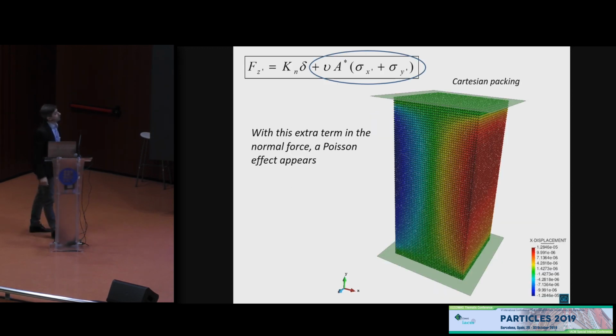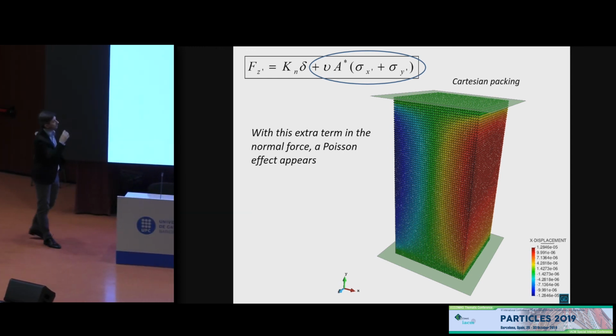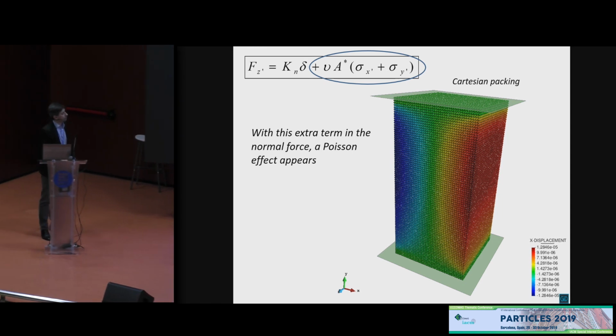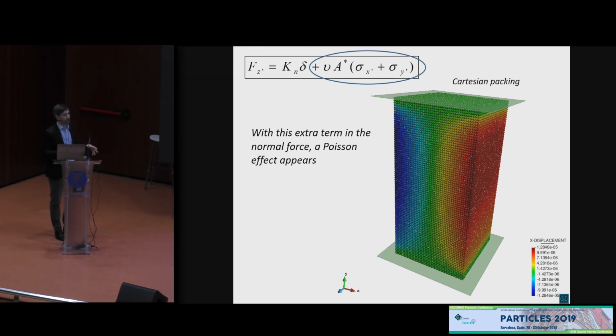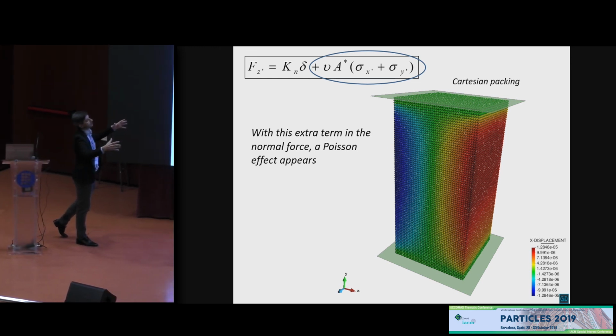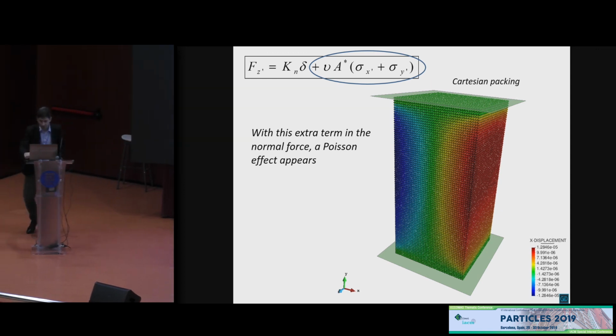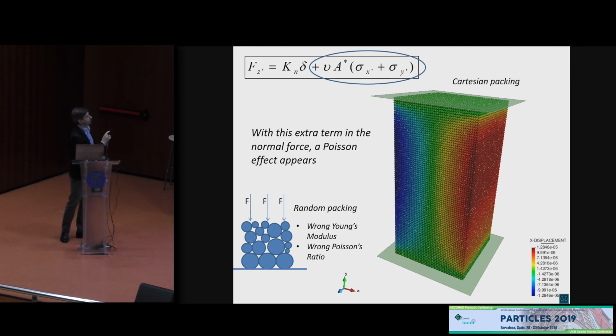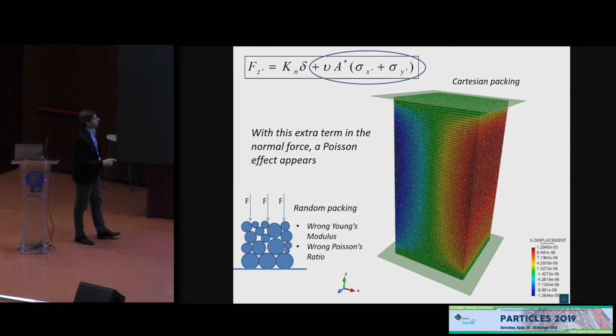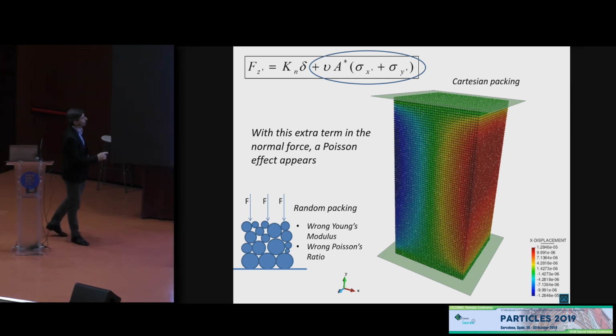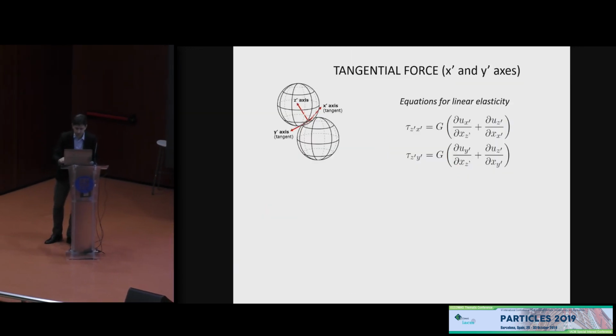Okay, when we did this with a Cartesian packing, we recovered the correct Poisson's ratio. That's the first time I see that, because usually in order to get some Poisson ratio, some lateral strain, you need to have always some random packing, or at least staggered packing. But that's done with the Cartesian packing. I mean, they are columns of spheres, and they are still expanding thanks to that term. However, for the random packing, we are still depending on the tangential stiffness. So we are getting a wrong Young modulus and a wrong Poisson ratio.